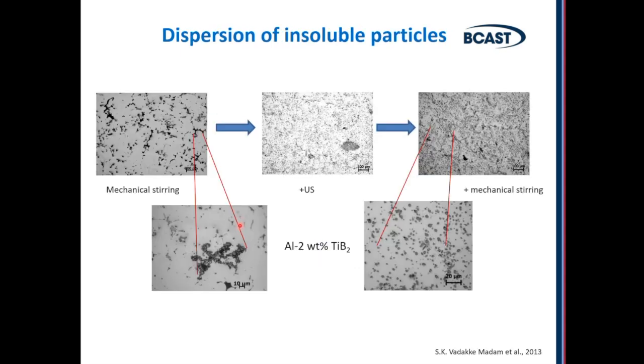So these are examples of dispersion of insoluble particles. If you just do mechanical stirring, this is TiB2, titanium boride particles in aluminium. Just mechanical stirring gives you a lot of agglomerates. If you do ultrasonic processing, you have much better dispersion of these particles. If you do both ultrasonic processing and mechanical stirring, you have quite good distribution of particles which are deagglomerated and evenly distributed in the matrix.